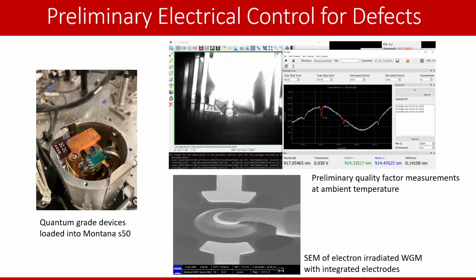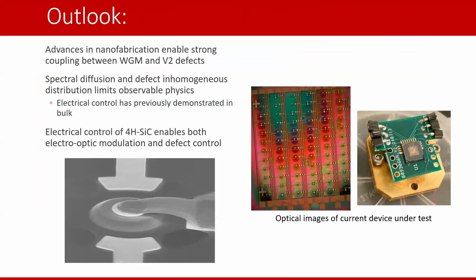Preliminary measurements show, unfortunately, lower quality factors than I was hoping. This is for a 10 micron diameter device, with a quality factor of 95,000. This is because I put the electrodes a little too close. So instead of being separated by 8 microns, these are separated by 6. And that's a little too close to the optical mode, so you get loss from the electrodes here. But this should be completely sufficient to see defects within the cavities. And so the devices you can see loaded. These are measurements from room temperature. It's cold now, so I will be measuring those in the coming weeks. And hopefully I will be very excited to tell you guys about it.